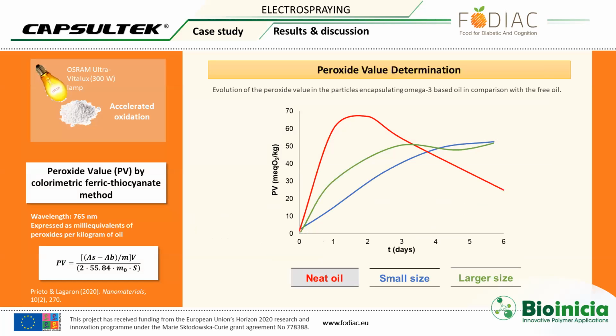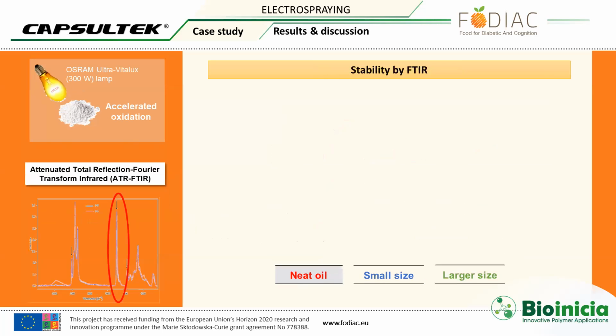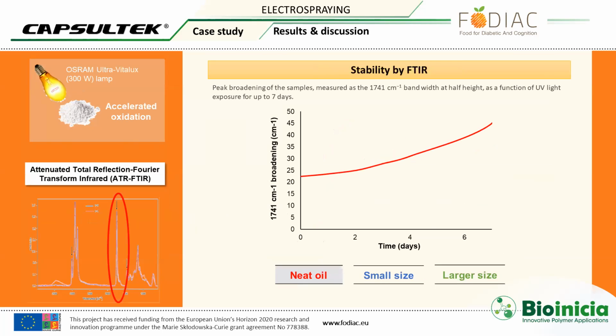We have characterized the particles. We performed a stability test to UV light, and this test was characterized in terms of the peroxide value, and we have observed that the capsules have much more stability than the free oil. And similar conclusions were obtained with the FTIR study.